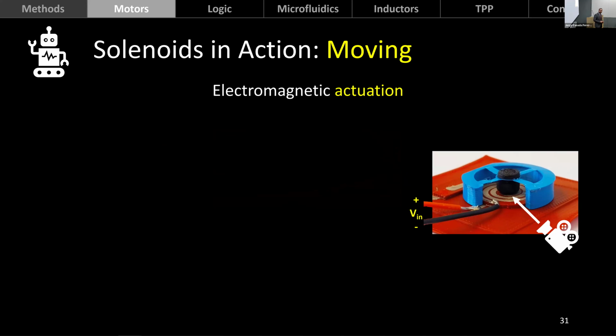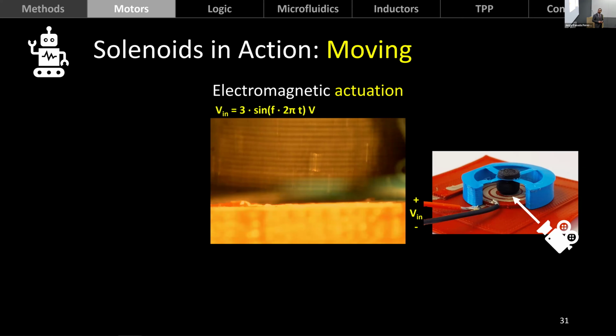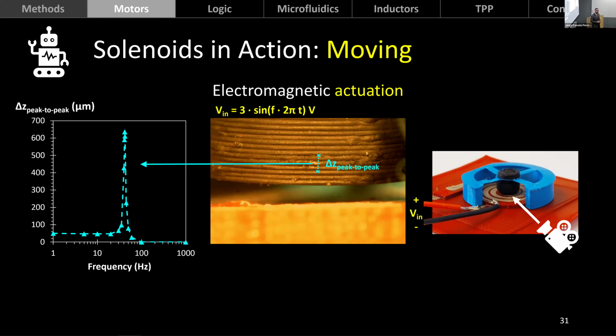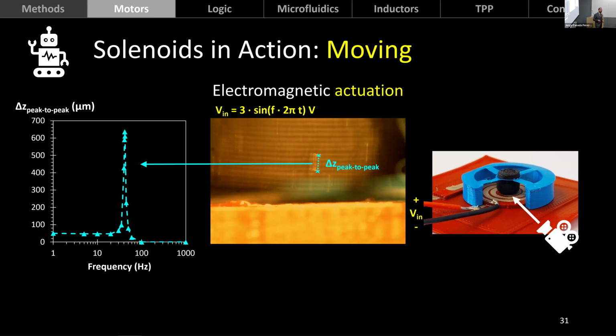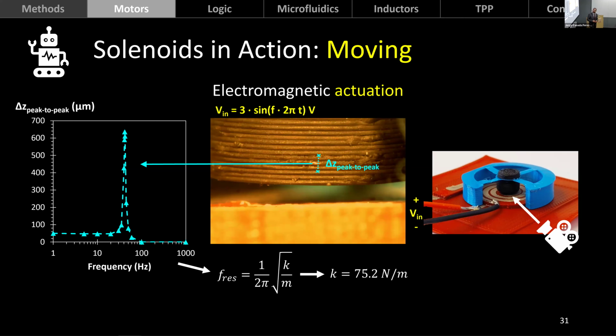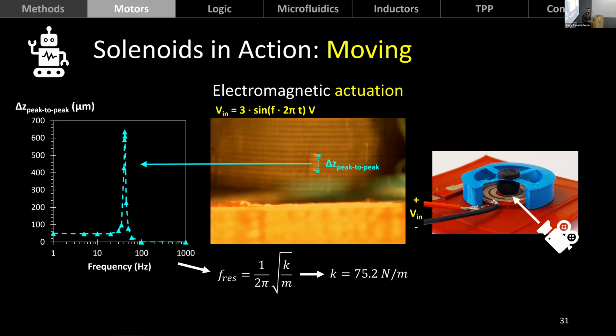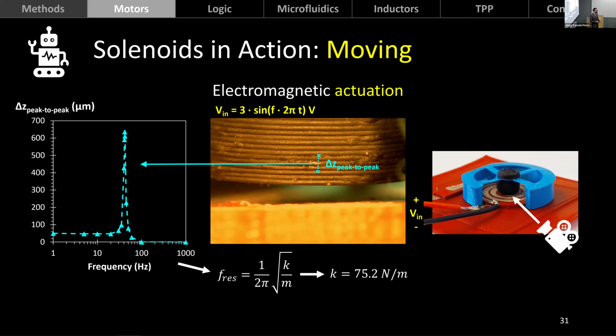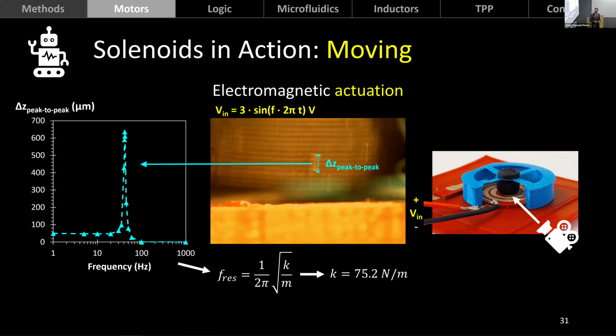And we also excited this by introducing a sinusoidal signal. And with that, we made it oscillate. And by measuring the amplitude of that oscillation, we were able to characterize the frequency response of this device, including figuring out the resonant frequency of this device, at which it oscillates a lot more than at any other frequency. And from that, we were able to do a little further characterization, for example, finding the spring constant of this particular device at 75.2 newtons per meter. And this type of data will help us inform future designs of this type of device.